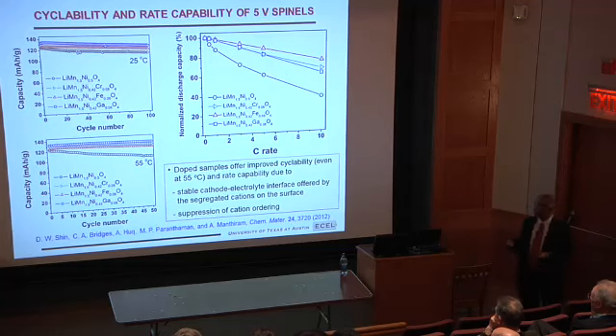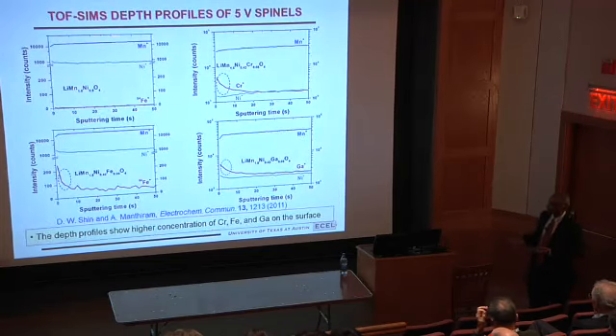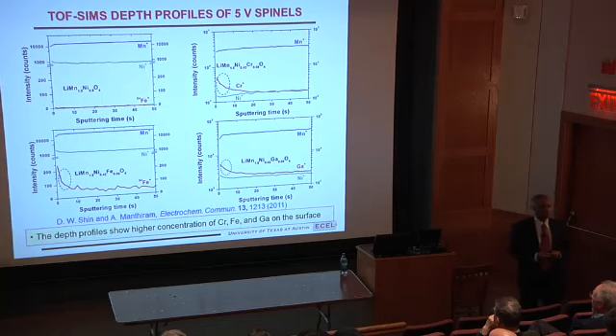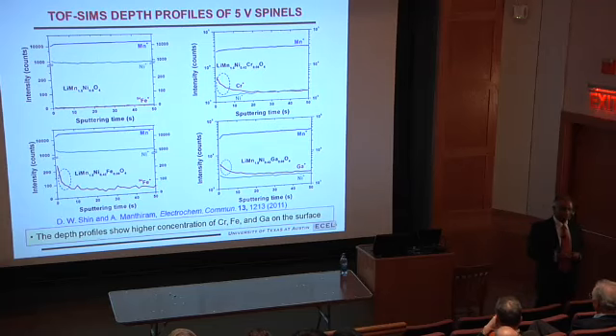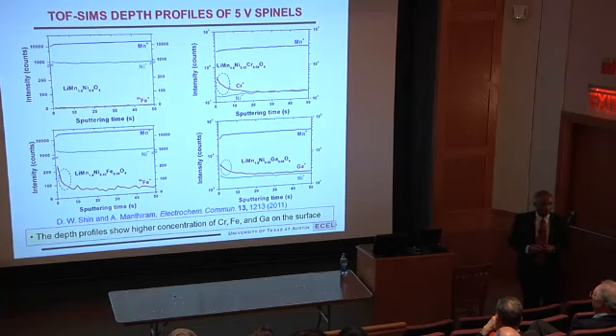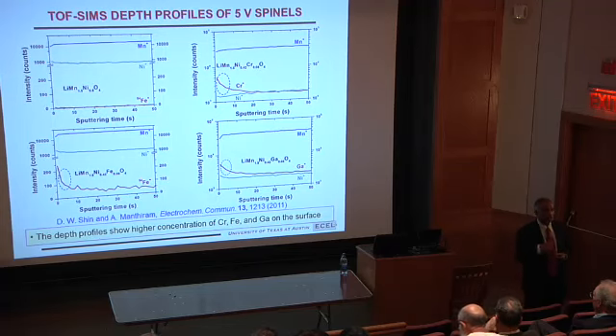You have better performance. Also, the doped material has better rate capability than the undoped material. So doping helps because of a few things. Because of suppressing the ordering, eliminating the impurity. More importantly, we have done a lot of XPS as well as time-of-flight secondary ion mass spectroscopy. This is an underexplored area in the battery community. When you dope with these things, it turns out certain ions preferentially segregate to the surface. I was talking about it earlier. So when these ions are on the surface, some of them are much friendlier with the electrolyte. They don't react that much with the electrolyte. So you have a better, more stable, robust electrode-electrolyte interface. So that helps a lot.